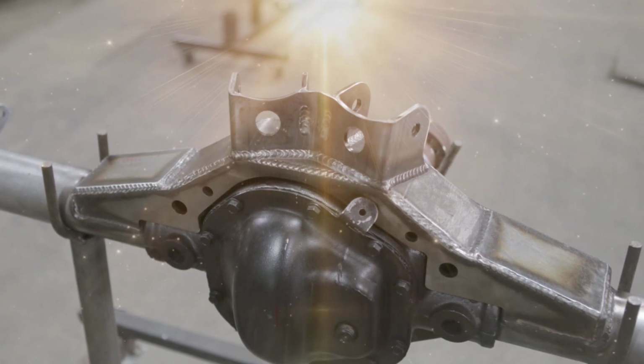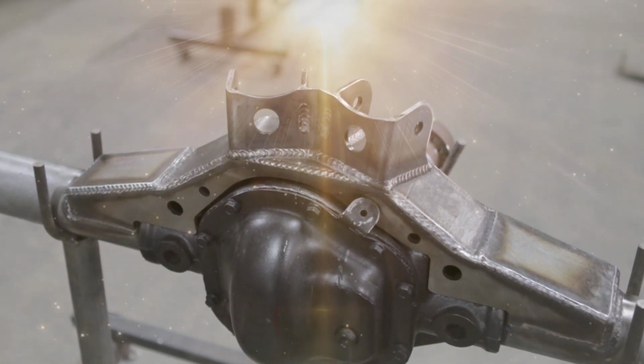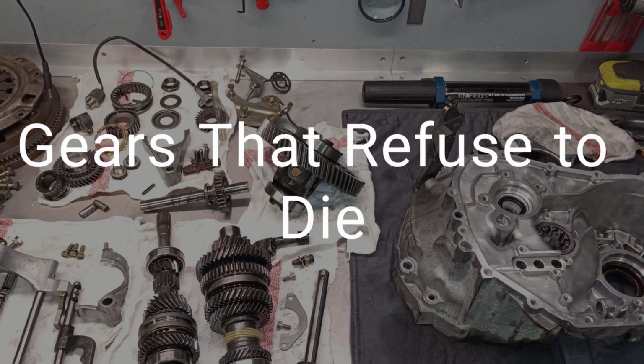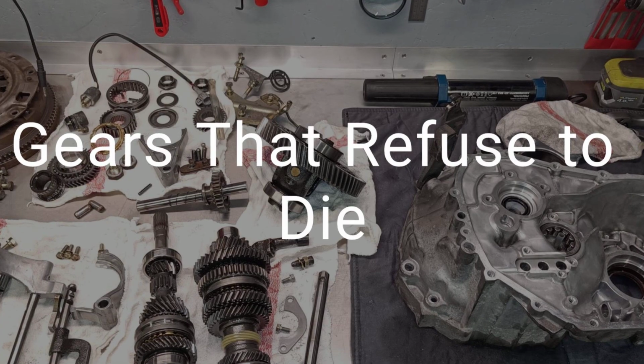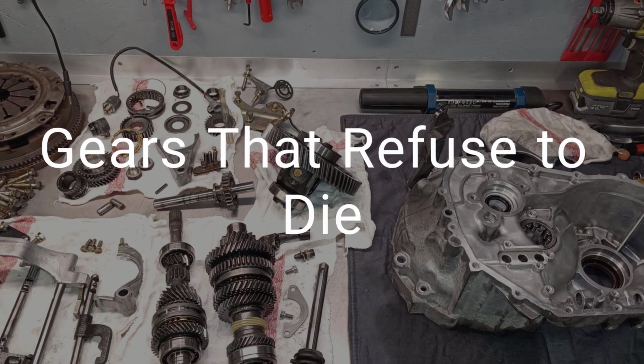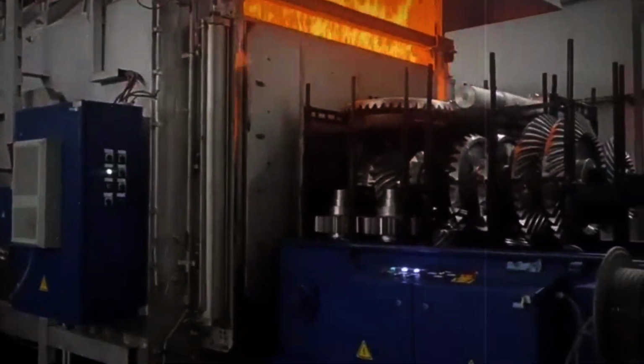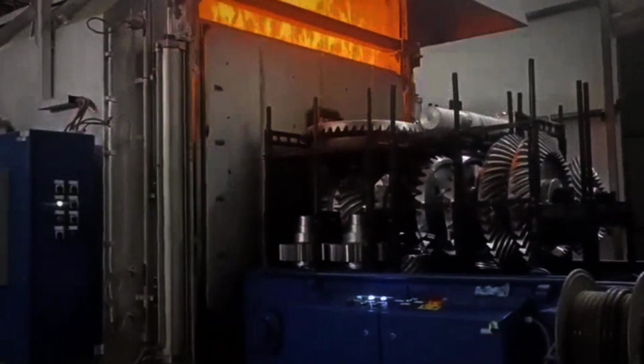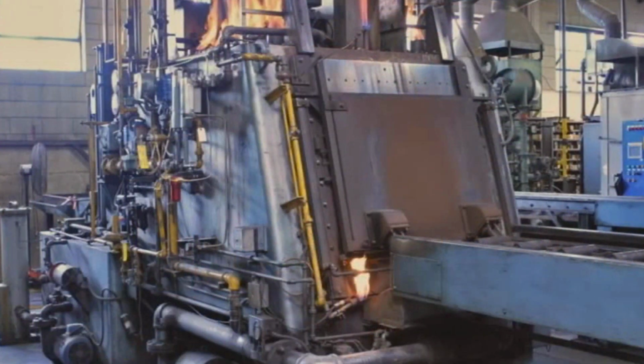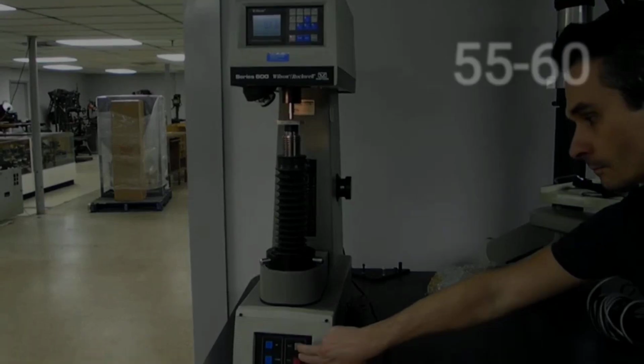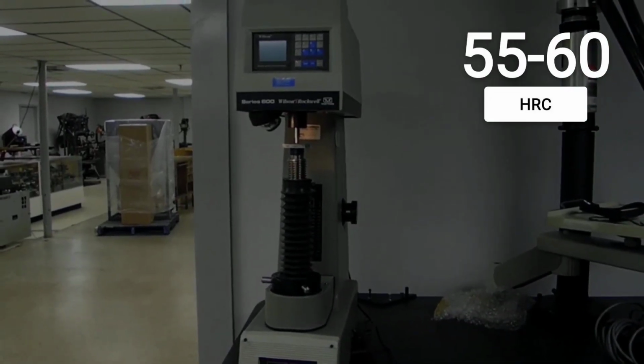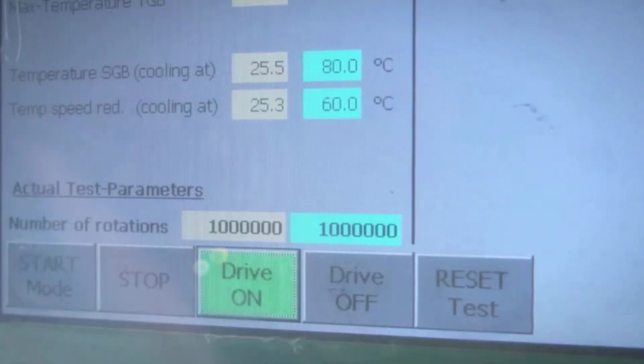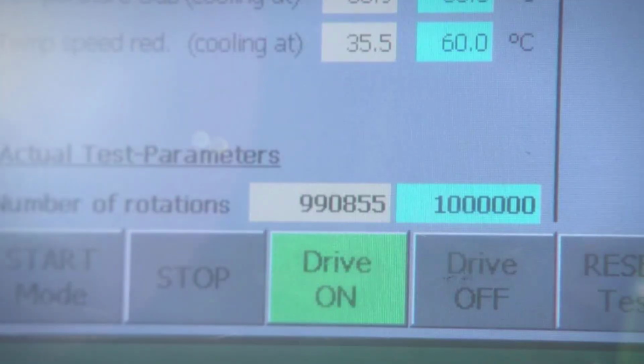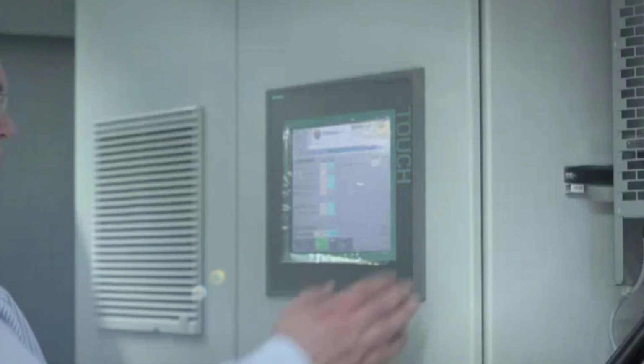As a result, the differential housing often outlasts the rest of the drivetrain, quietly surviving long after the gears inside have been rebuilt. Number 2. Manual transmission gears have quietly built a reputation for outlasting nearly everything else in the drivetrain. At the heart of their longevity is 8620 carburized steel, a low alloy blend that undergoes a deep heat treatment to reach a case hardness of 55 to 60 HRC, hard enough to shrug off decades of shifting, yet tough enough inside to absorb shock loads without fracturing.